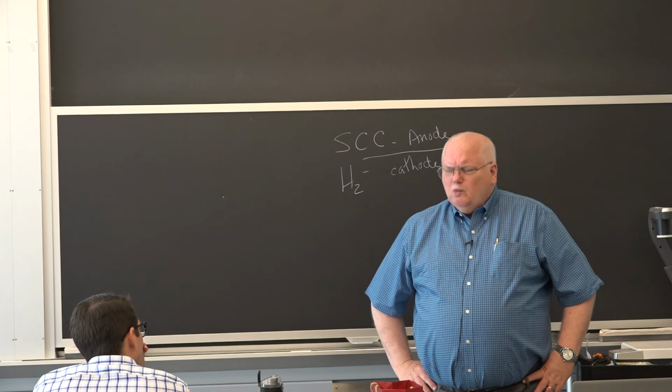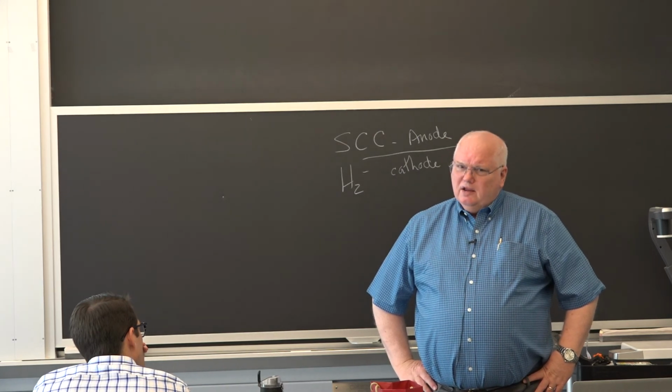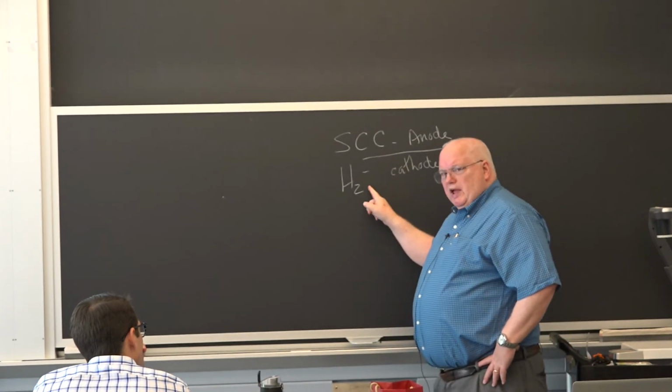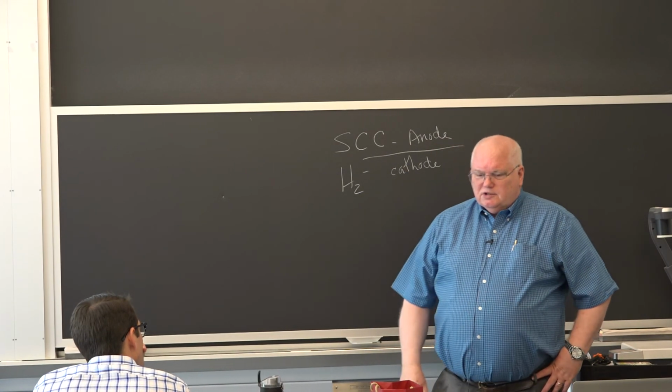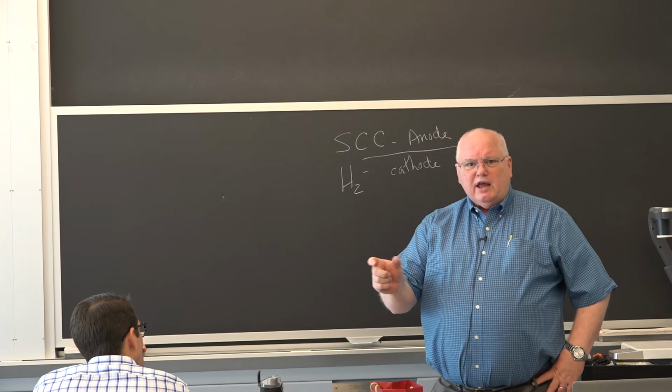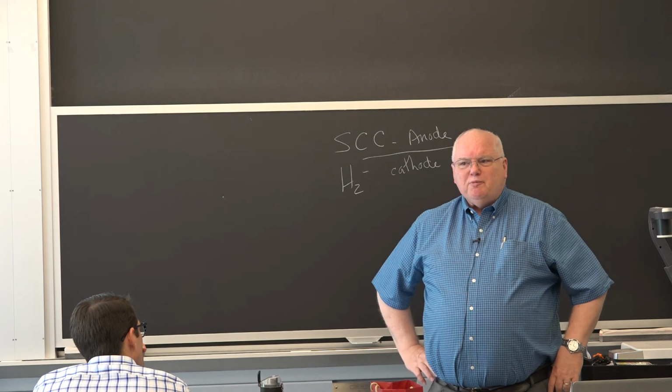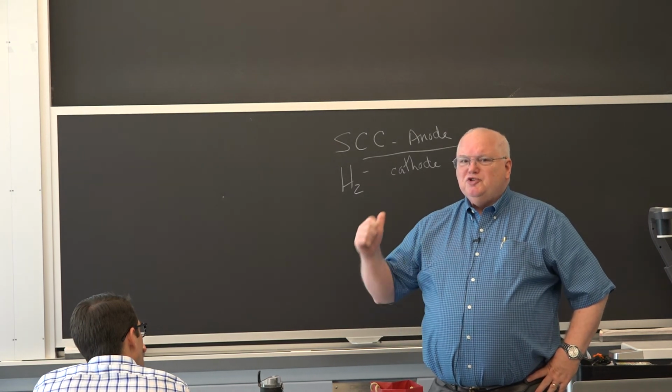And finally I thought, well, maybe that paper I read got it backwards. And it wasn't stress corrosion cracking. All we had was hydrogen embrittlement. So I said, change the alligator clips on our little setup. Bang! Within 5 minutes we cracked it from hydrogen embrittlement.